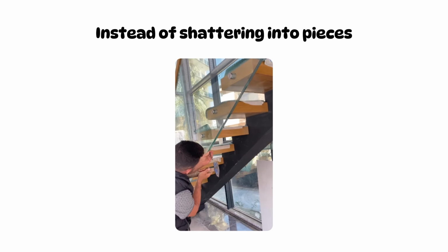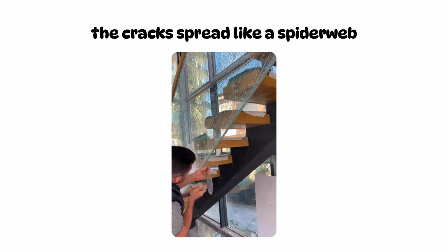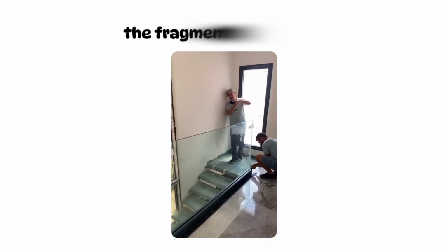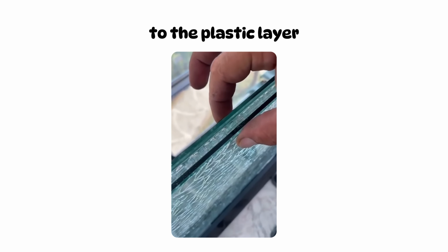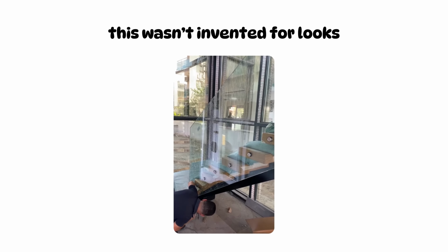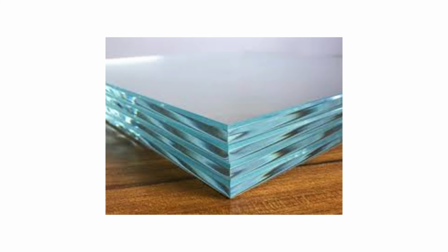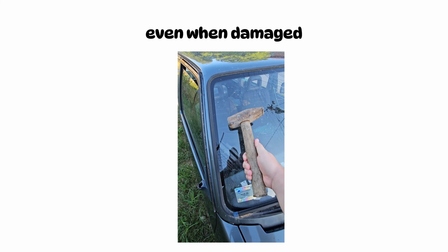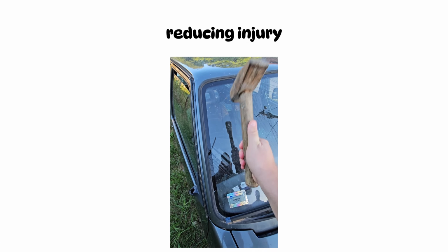Instead of shattering into pieces, the cracks spread like a spider web across the surface. The fragments stay stuck to the plastic layer. This wasn't invented for looks, it was invented for safety. Early car windshields used regular glass, and accidents often resulted in glass shards flying directly at passengers. Laminated glass solved that. Even when damaged, it stays in place, reducing injury.